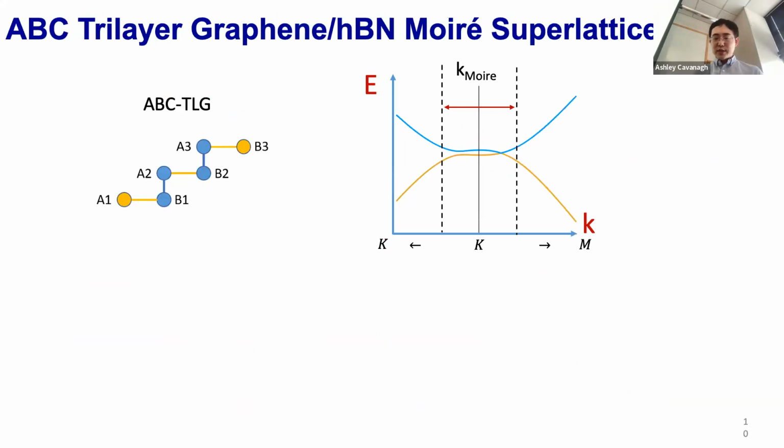So as we said, the lore we learned from previous experience of electron correlation in different systems is that we need to get a somewhat flat band. In trilayer graphene, here's how it works. You have a band dispersion that's roughly k to the cube. It's somewhat flat, more flat than a parabolic band, but probably not flat enough. And here's how you can make it more flat and eventually drive correlation.